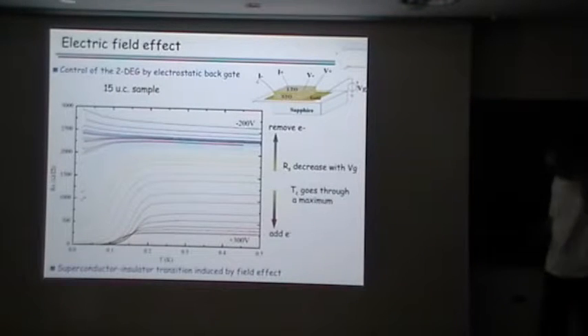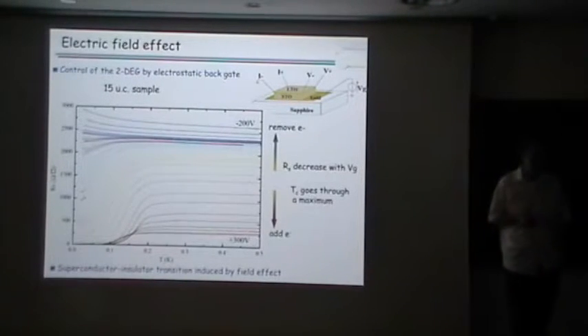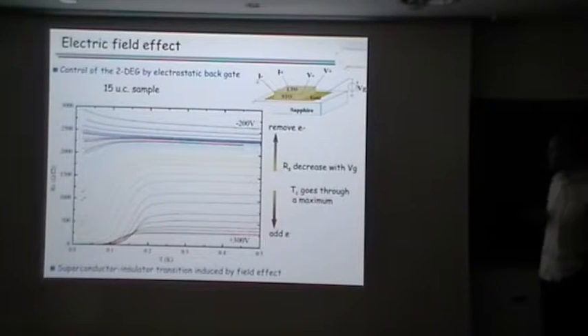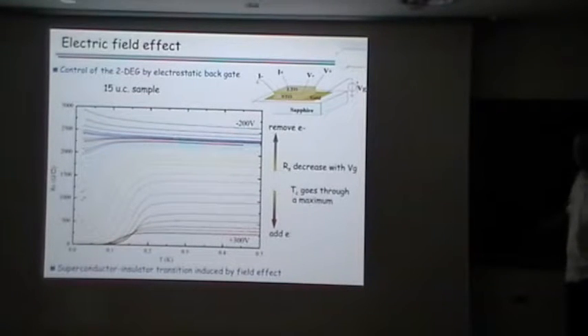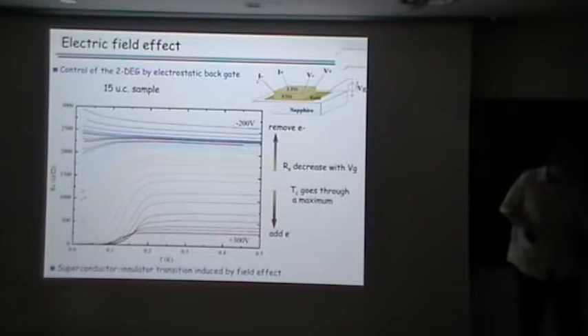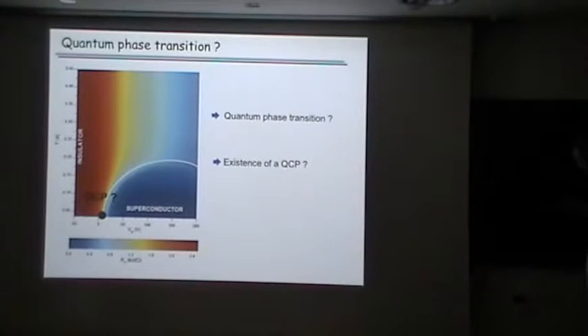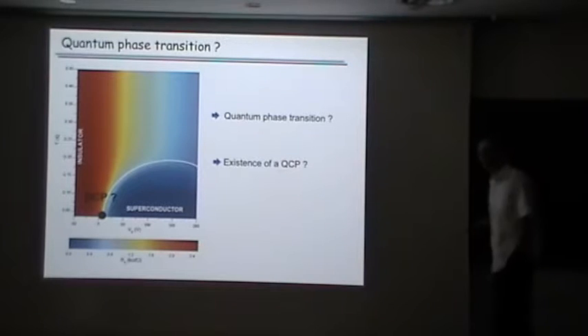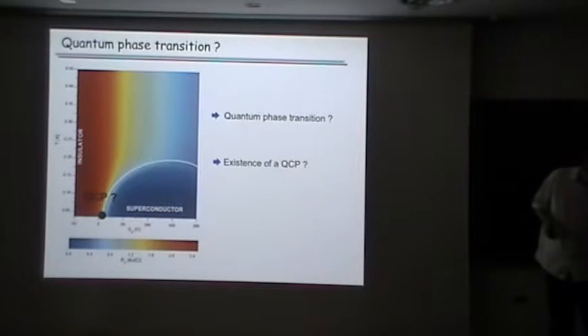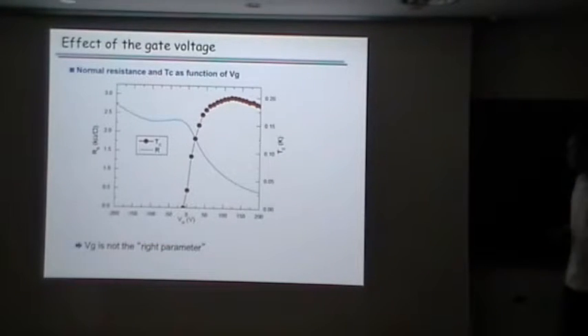Okay, now since we can put a gate voltage, we did the same kind of experiment that the Tristan group did and others in the literature. And of course, we also are able to modulate the superconductivity and the resistivity on a large scale when we remove or add electrons. And we can do also a very nice phase diagram where you have here the insulator, where there's a negative slope, here the superconducting dome, and then here again, is this a quantum critical point? Can we have evidence of that? If we look closely at the data, we see this. That means in our system, clearly the resistance goes down here, and then there is a kink at 0 voltage. And Tc goes down at exactly the same point.